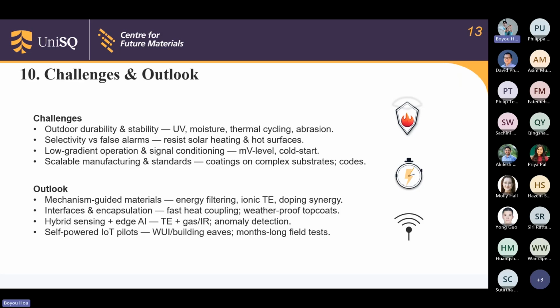Here are still some challenges. The first is outdoor durability and stability. Sunlight, moisture, thermal cycling, and abrasion can change the film and the adhesion on real surfaces. The second is selectivity versus false alarms. Sensors must ignore sun-heated metal and hot pipes, but still react to early fire heat. That needs smart placement, good interfaces, and clean thresholds.